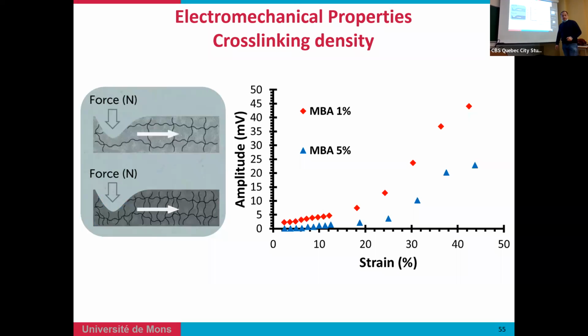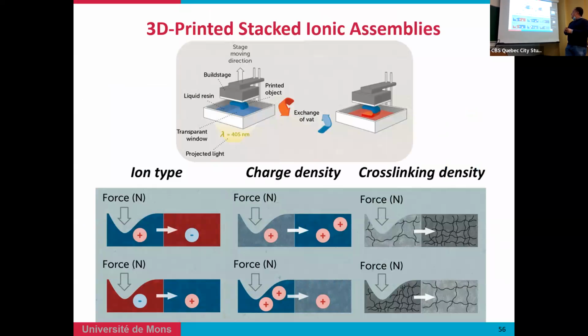Of course, the crosslink density is also affecting the mobility. If you use a less crosslinked system, with 1% of crosslinker, you have very good mobility. When you crosslink too much the system, you reduce the mobility, so the signal amplitude is reduced, as shown here in these examples with the curve.